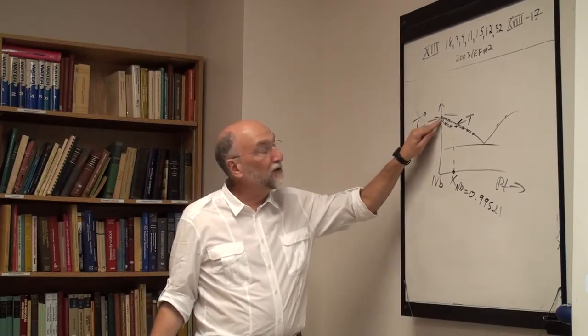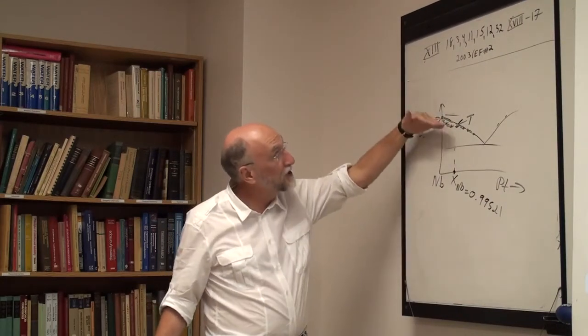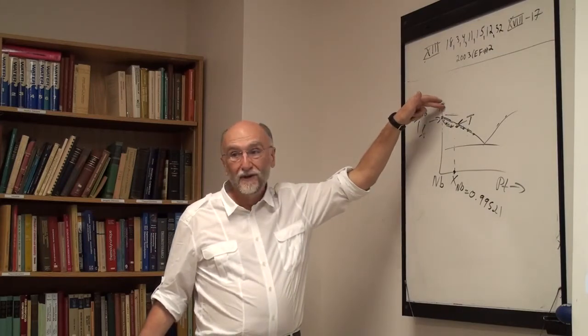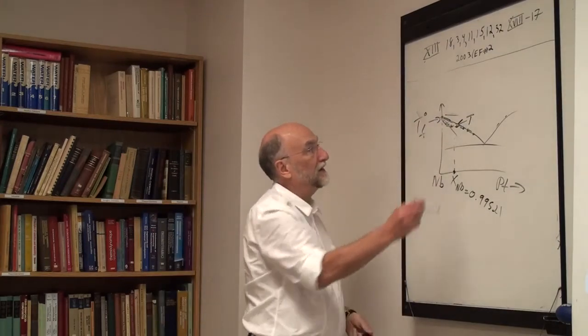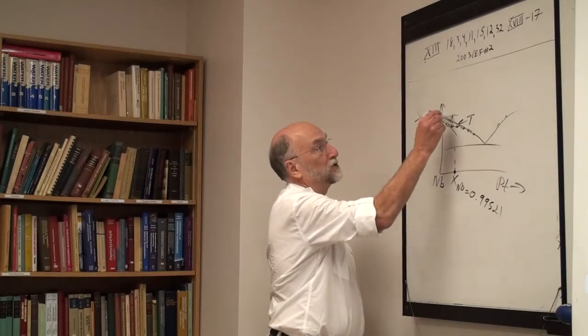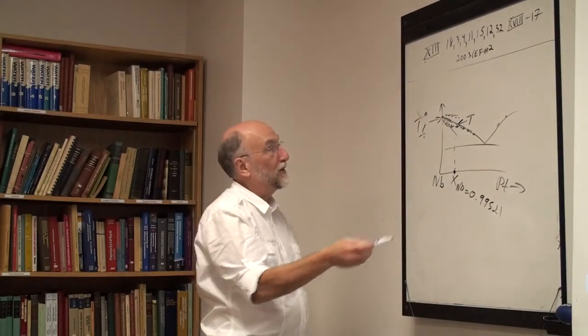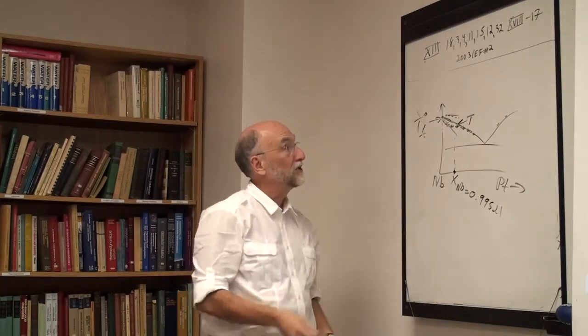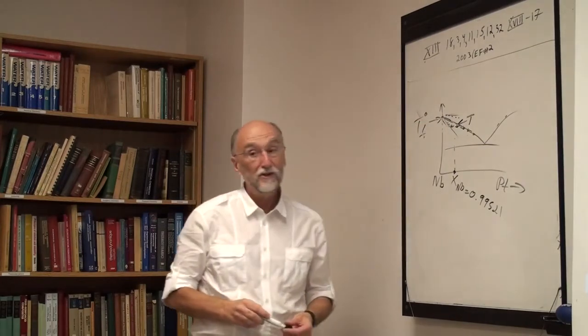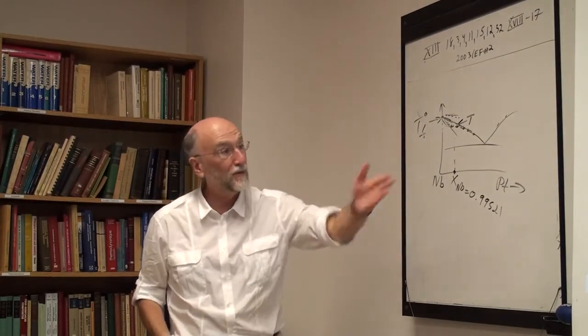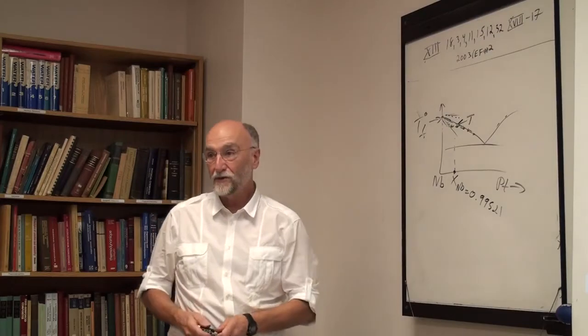As you reach the limit, they have no effect. This limiting region is determined by the ideal term. Okay, and if this goes down like this, then if your measured points were up here, and you trusted the measurements, then that probably indicates you have solid solubility. If they're down here, probably there's just something wrong with those measurements, or maybe something wrong with your heat diffusion, or something's not right.